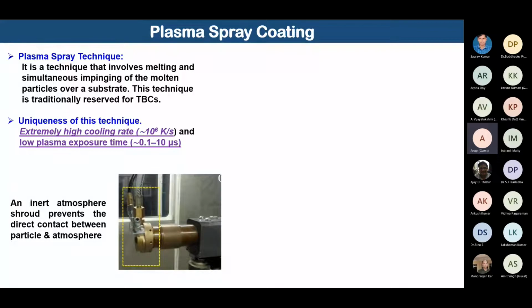Let us see here in the plasma spray technique. If we talk about the major novelty or uniqueness of this technique, it is an extremely high cooling rate, meaning 10 to the power 6, or 1 million Kelvin per second. When we talk about that high a quenching rate, the chances of oxidation of the powder particle at high temperature are very minimal, because yes, temperature is involved, but the plasma exposure time is in microseconds.